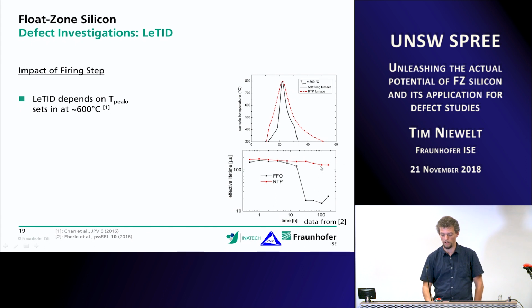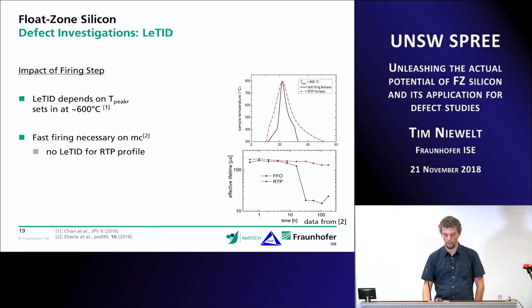And we found out that the RTP processed samples, although they have seen the same peak temperature, just don't degrade, indicating that this difference in the firing profile, in the temperature rates, strongly affects the degradation. So yes, we've seen that fast firing is necessary in multicrystalline silicon, and there is no degradation for the RTP profile.